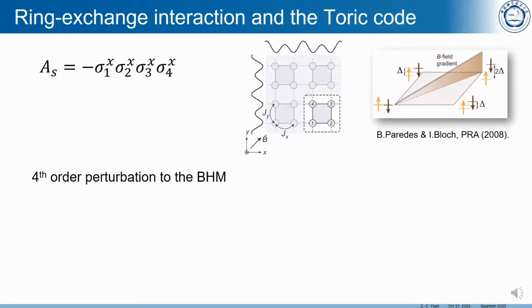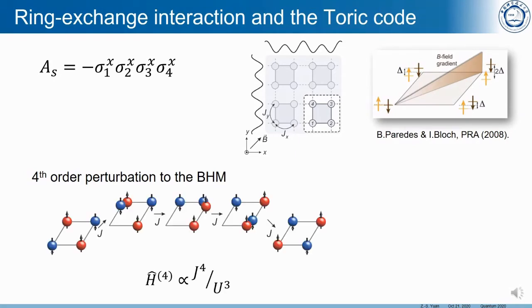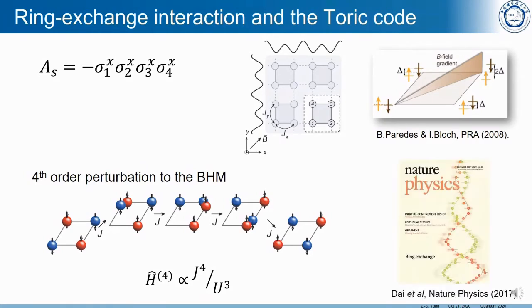Furthermore, based on the spin-dependent superlattice along two directions, we achieved an array of plaquettes, and within each plaquette, we applied the local magnetic gradient to suppress single tunneling and super exchange interactions. For the first time, we realized a system which is governed by the fourth order perturbation to the Bose-Hubbard model, and this is the minimum Hamiltonian of the toric code model, which will be very useful for fault-tolerant quantum computation and for creating topological matter.